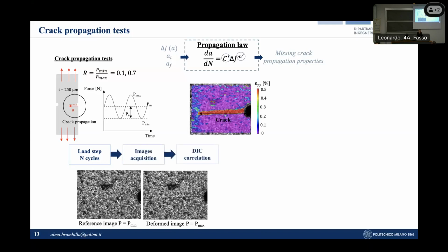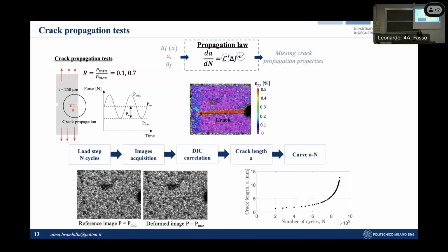These images were then correlated through digital image correlation to compute the crack length at each step. And so it was possible to obtain the evolution of the crack length as a function of the number of fatigue cycles from which the crack growth rate was obtained.